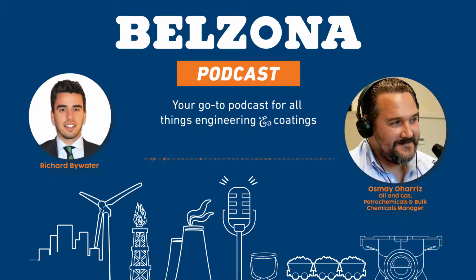And we know that at 20 degrees C it is excellent. We test again at 90 degrees C, and we see that at the same concentration it is still excellent. That gives you a strong indication that it might actually be fine if your concentration increases a little bit more, or if the temperature goes beyond 90 degrees C at a lower concentration, for example. So there are different things that you could definitely consider to make a proper estimate as to what we might actually see.